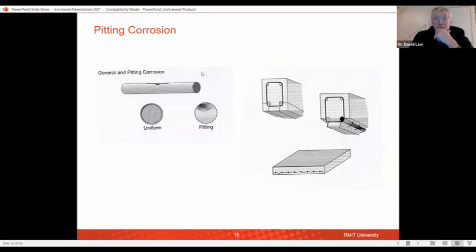And these are what the problem is, that when we have chloride attack, we get what we would call pitting corrosion. That is, it corrodes at very small specific points on our steel. And these pits mean we can lose a lot of section of our steel. This is uniform corrosion. This is what we tend to get if we have carbonation attack. The same amount of steel has been lost in both of those bars. However, you can see you've lost a lot more cross-section in this bar, which tends to come from chloride attack, than you would from carbonation attack.